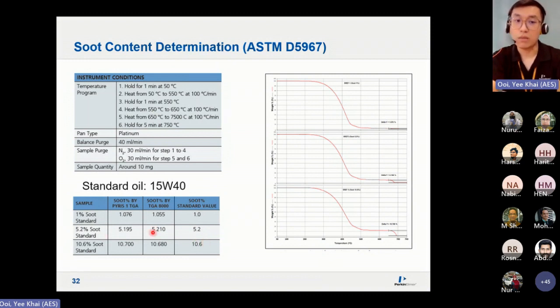So this is a standard, meaning with known soot values. Then we use TGA to verify it, and you can see you can get very, very close. This is doable for high percentages, no problem, even if you're using a not-so-sensitive TGA. But as you go lower and lower, this is where you need a very sensitive balance, as we've shown you.